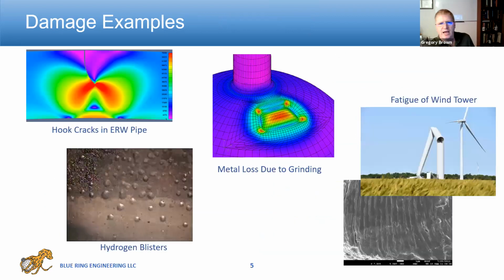Here's some just pictures of damage from various cases. In the upper left, you're looking at a computer model of what's called a hook crack in an ERW pipe. Electric resistance welded pipes very often get crackings at that weld. You get what are called J cracks or hook cracks. In service with pressure cycles, these can grow and can cause failure.